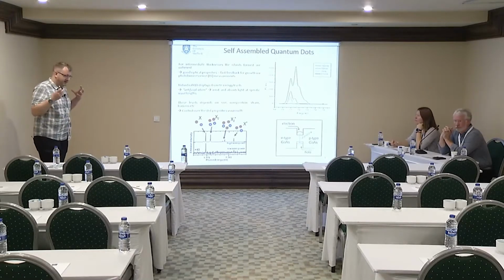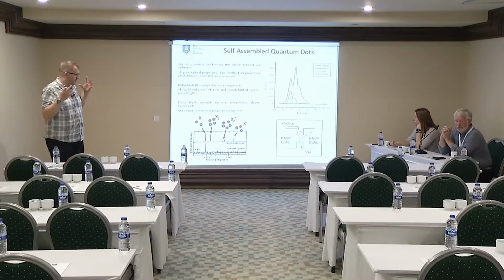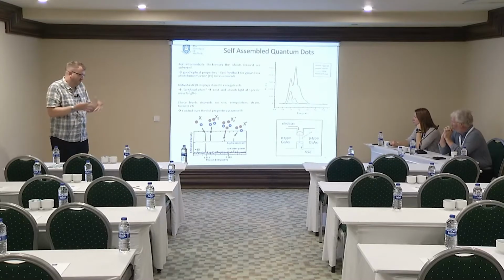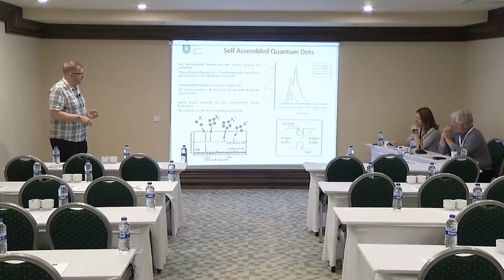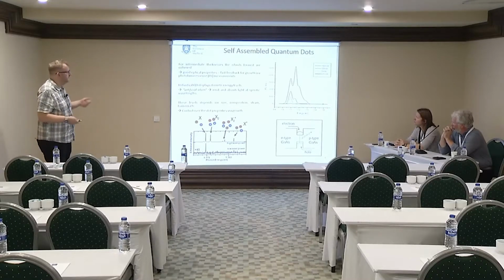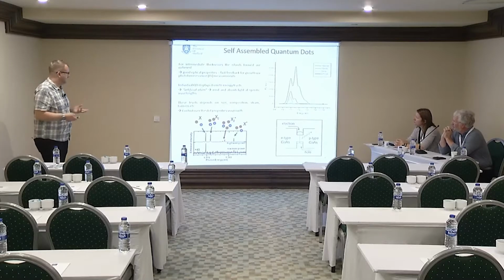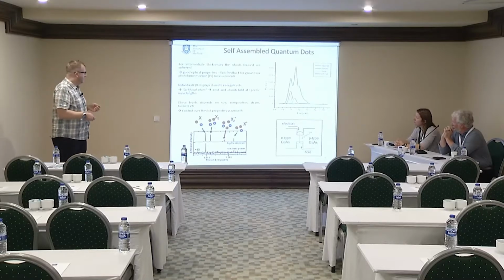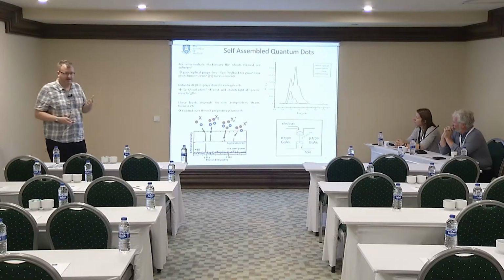What this has done is, in a standard semiconductor, we have an object which is 10 to the 4 atoms or slightly larger, where we can have a single electron and hole, and we can manipulate them. We can create devices where we just inject electrons and holes, making lasers or LEDs, or we optically excite them to get luminescence. And we have a controllable atom, if you like, because the size, composition, strain, and the barrier materials are going to move our energies around, which means we can attack different wavelength ranges for different problems.